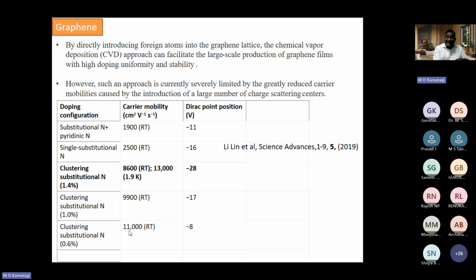But still it is less than the intrinsic mobility, and the intrinsic mobility of graphene is around 12,000 centimeters square per volt second. So to enhance the mobility, doping is not a good idea in the case of graphene. But to enhance the electrical properties of compound semiconductors like gallium arsenide and gallium nitride, doping is significant and is a very good idea. But in the case of graphene, doping is not at all a good idea to enhance the electrical properties.